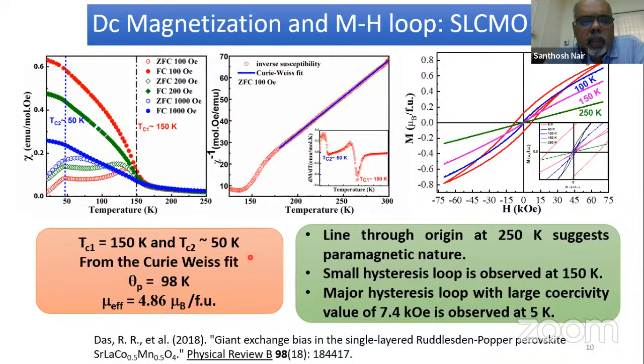These are the fit parameters: theta p of 98 K, and a positive theta p shows that there are ferromagnetic correlations in the system, and the mu effective is found to be 4.86 mu B per formula unit. Okay. The hysteresis loop shows a large hysteresis at very low temperature. At room temperature it is like a paramagnet, as you expect. But at very low temperature you can see a hysteresis loop, showing there's a bit of ferromagnetism involved. And these two transitions can also be seen in the first derivative of the curve. You see these peaks corresponding to the two transitions.